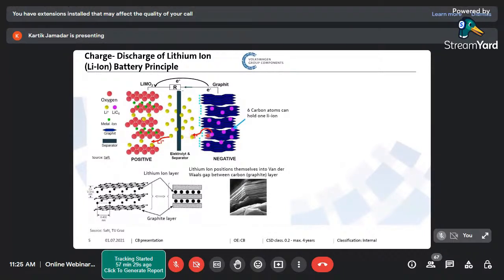The same thing happens at lower cell temperatures. Normally, down to minus 7 degrees centigrade, the lithium ion cell works with very good efficiency of around 97%. But if you go to lower temperatures, the efficiency is irreversibly affected. Why? There is an electrolyte here, and it has a very important constituent called ethylene carbonate. Normally, the electrolytes we know from other batteries are water based. Here, we have a non water based, carbonate based electrolyte. Ethylene carbonate has a eutectic point at minus 7 degrees centigrade. It means that if you go lower than that, it will solidify.